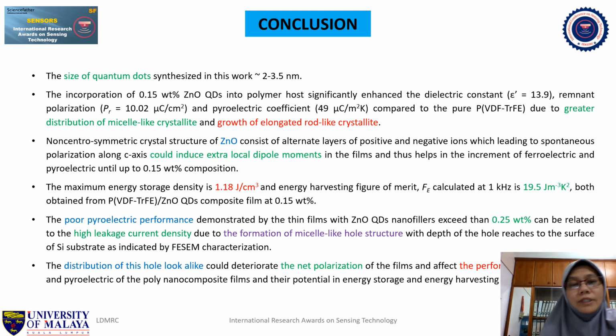So as a conclusion from this work, we can confirm that the quantum dot size is 2 to 3.5 nanometer, and when 0.15 weight percentage of zinc oxide quantum dots are incorporated in the polymer host of PVDF-TrFE, it has produced enhancement in dielectric constant, remanent polarization, and pyroelectric coefficient compared to the pure PVDF-TrFE. This is probably due to the greater distribution of micelle-like crystallite and also the optimized growth of elongated rod-like crystallite.